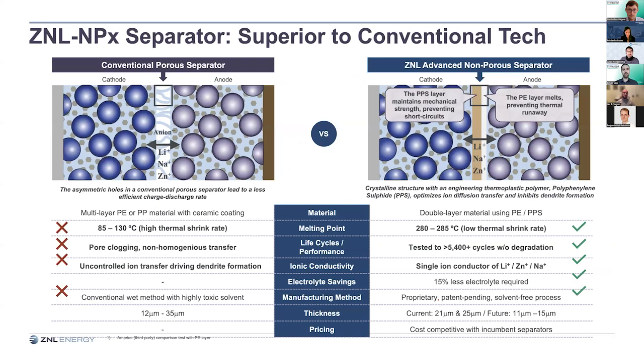So what's the difference between the conventional separator and ours? The conventional separators are porous, meaning they transport the ions through microporous structures and electrolytes. Ours is a PPS, it's non-porous, meaning it transports the ions through something called diffusion. There's a crystalline structure inside the PPS where the ions transport, and only the ions that you want to transport, even if it's lithium ions, sodium ions, or zinc ions.